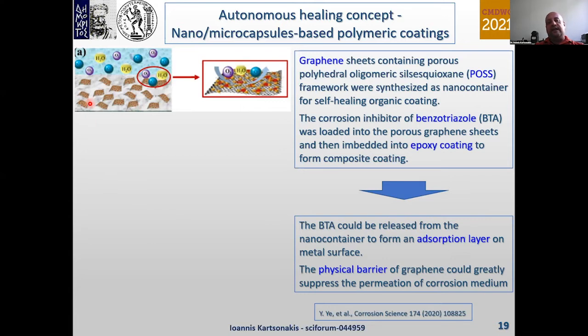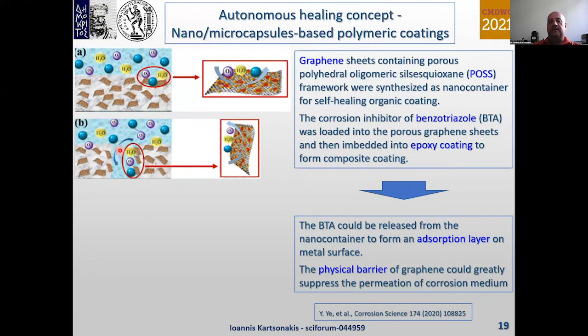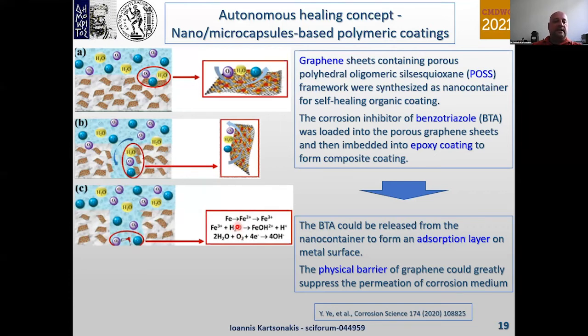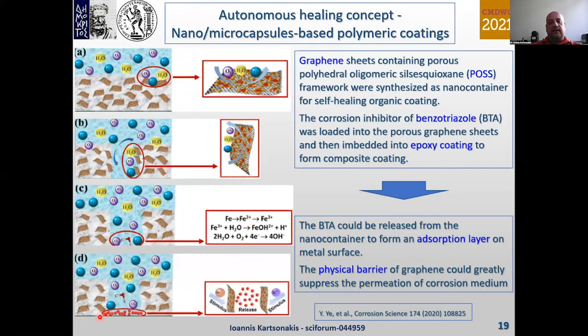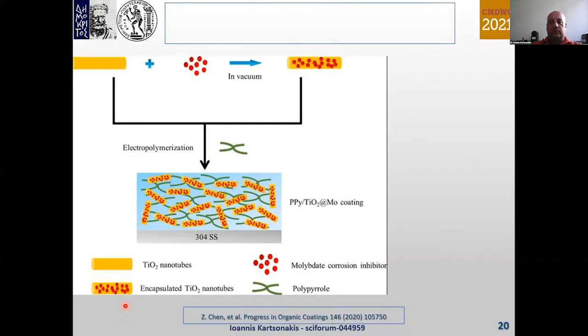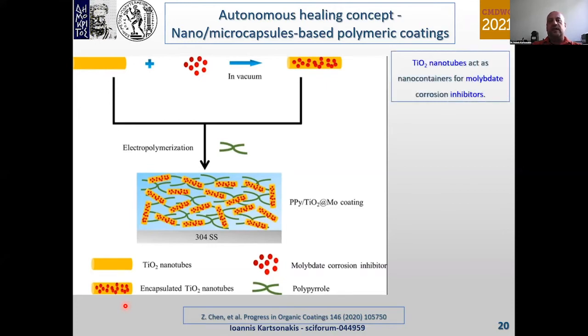We can see here the intact coating included the graphene sheets that were loaded with the corrosion inhibitor. After the formation of the damage, there is an insertion of water molecules, oxygen and chloride anions. The corrosion starts. Here we can see the reactions, but there is a triggering of the graphene sheets and the release of the inhibitors, and the corrosion stops. In the work of Chen in 2020, regarding also autonomous self-healing based on nano and microcapsules, nanotubes were fabricated from titanium dioxide, this one, and they were loaded with inhibitors that were based on molybdate.